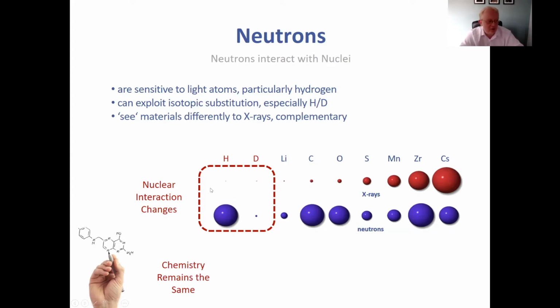If we want to do a spectroscopy measurement where we're interested in the energy loss from the neutron after it's interacted with our material, then we keep the hydrogen in there, and the hydrogen has a very good incoherent scatter and shows up very strongly. And so we do different experiments with different isotopes to get different sets of information, depending upon the nature of the experiment that we're performing. Now it says down here chemistry remains the same when you switch between deuterium and hydrogen. That's not necessarily true. Definitely deuterium weighs much more than hydrogen, and so there is a difference in kinetics depending on the processes you're looking at. But generally speaking, it's very, very similar.